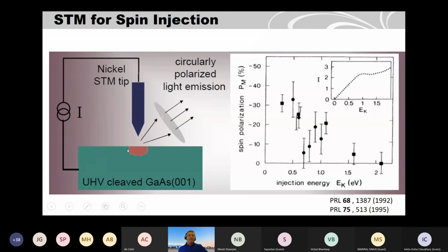So how could they do that? This is gallium arsenide, and this is an STM tip with a nickel tip. They prepare it in ultra high vacuum. So it's a ferromagnet tip at the end. You can apply some bias to inject spins here, and then you look at the light emission. So the polarized light comes out, and you can detect the polarization. Here the K means the energy of the injected electrons, and here you see the polarization. So all these experiments show that you can inject spins in the semiconductor and detect them by optical methods.